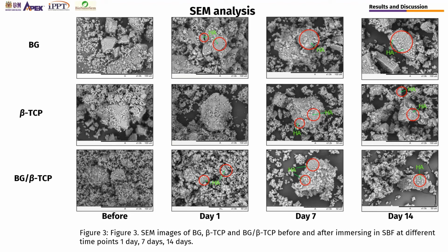To test bioactivity, SBF is the most effective in vitro testing method for apatite formation, and BG incorporated with beta-TCP may help to improve the bioactivity of the composite based on hydroxyapatite formation on the surface on day 1 after immersion. The XRD spectrum also recorded evidence of the combeite phase in the BG beta-TCP structure, which is supremely bioactive.